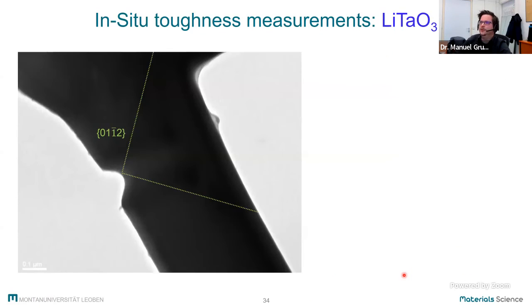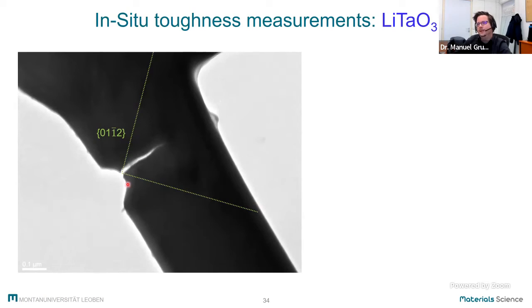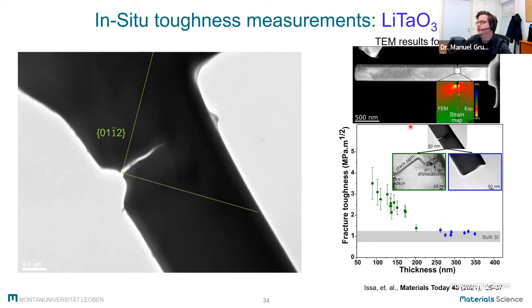But since we are interested in the plastic deformation behavior, we also went to the TEM, manufactured much smaller cantilevers, aligned the twinning planes under an angle where they see the highest shear stresses, and did our tests again. And again, we only see brittle fracture here, following the cleavage planes. So at this point, we were not successful, but at the same time, colleagues from Lyon did similar experiments on silicon. And what they could see was that for very, very small thicknesses, dislocations can nucleate and move in front of the crack tip, leading to an increased fracture toughness up to a factor of 4.